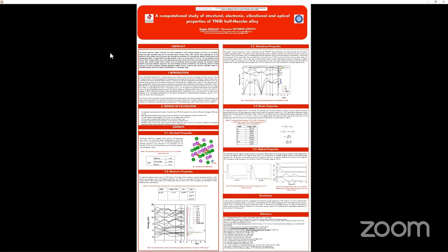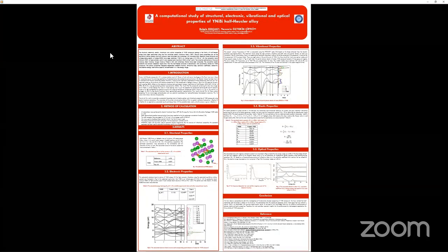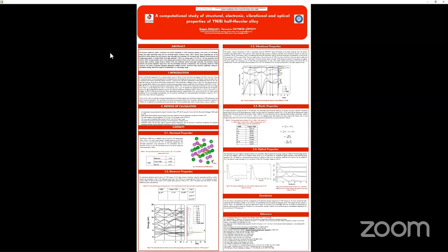Elastic properties of a material provide useful information about its hardness, mechanical stability, and dynamic properties. Unfortunately, there was no experimental determination in the literature of the elastic constants of this compound. It is found that our obtained elastic constants obey the Born stability criteria. So, it can be concluded that the considered phase is mechanically stable for the title compound. The analysis of the elastic constants enables us to obtain the bulk modulus, shear modulus, Young modulus, and Poisson ratio. The computed results of elastic properties are also listed in Table 3.